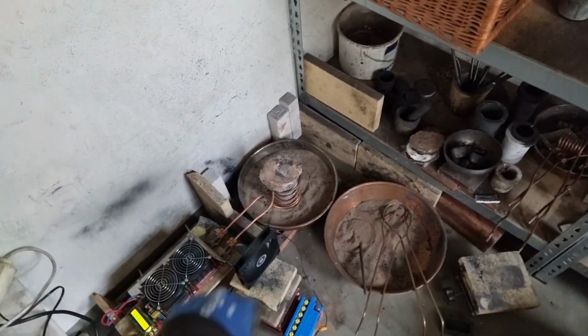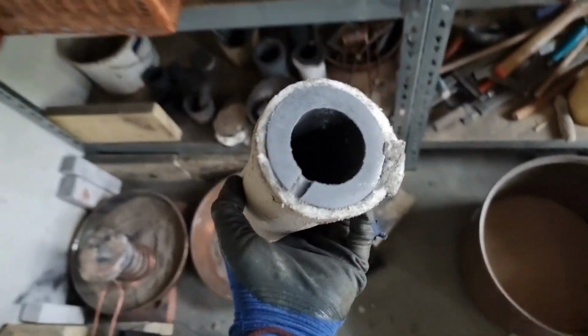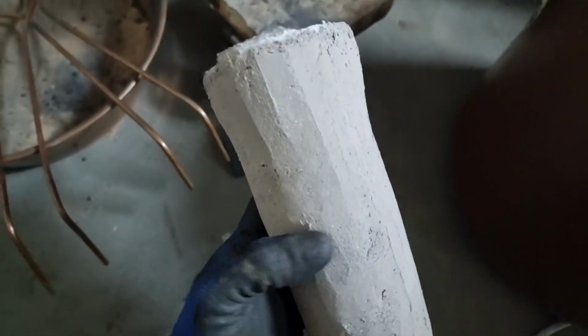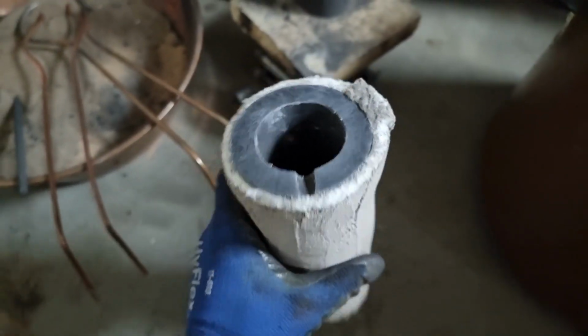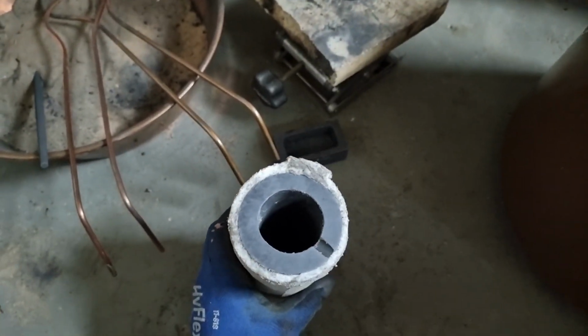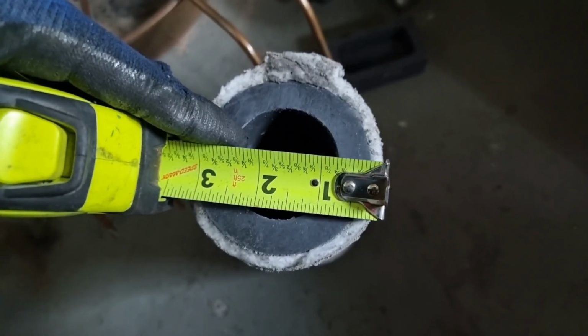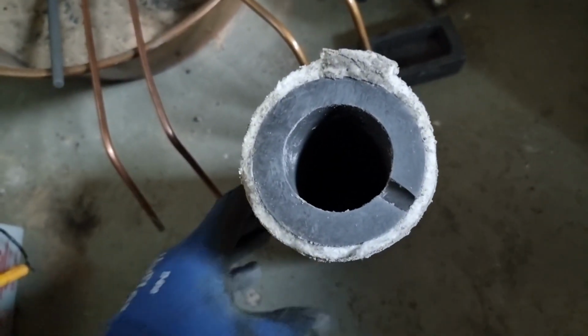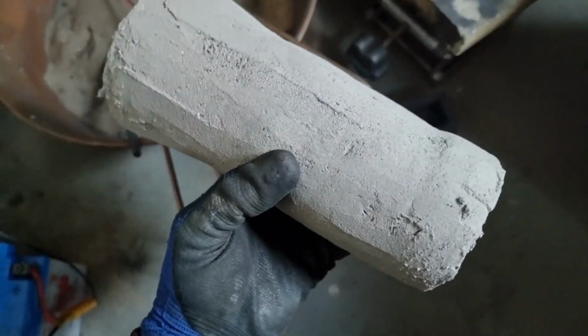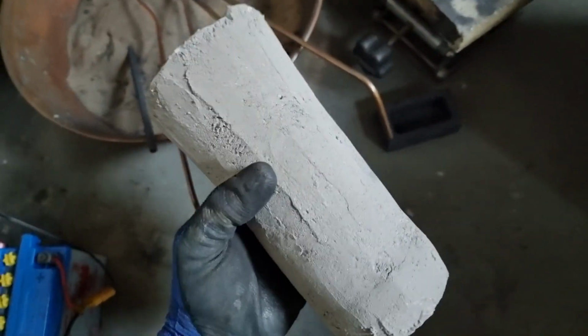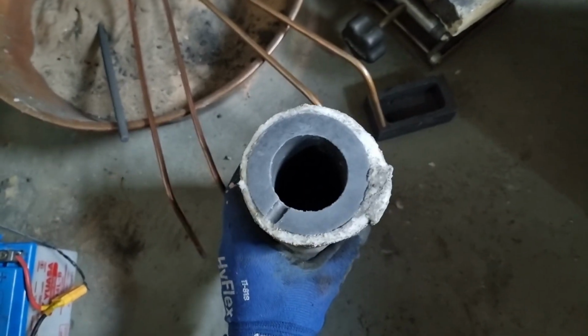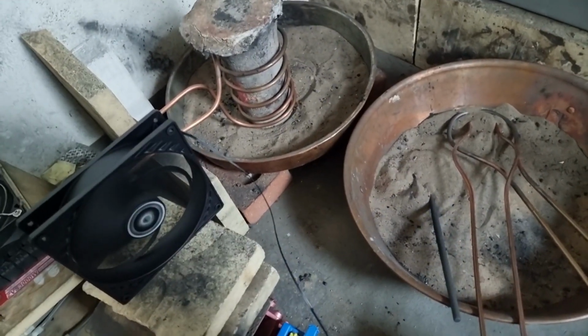So you put it all in a graphite crucible, a special kind of graphite crucible I'm going to show you in a minute. So let's see. That is essentially a 3 kilogram graphite crucible like that one, and that got covered with a thin layer of insulating ceramic wool, high temperature resistant up to 1400 degrees centigrade. So what we got here is about 1/4 of an inch of that wool, and then just a thin layer of high temperature resistant clay, essentially.